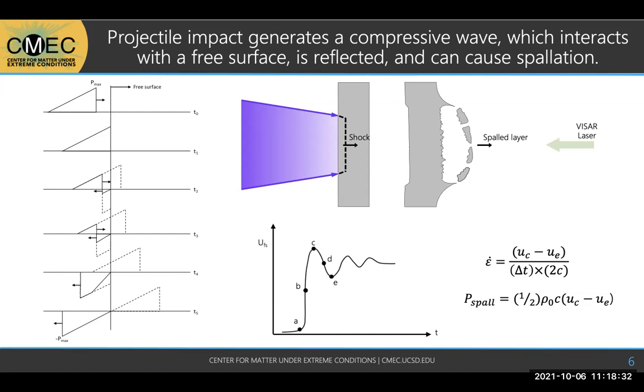So that peak velocity at point C and the pullback signal, which is point E, are used to calculate the strain rate and the spall strength. And then I have another example of this later, but I also wanted to bring up the point that, as I said, between point B and point C, you have kind of a doubling because that shock wave has entirely hit that back surface. You can assume that the peak free surface velocity is double the particle velocity. And so from the particle velocity, we use the Rankine-Hugoniot equations that I just showed to calculate the pressure.